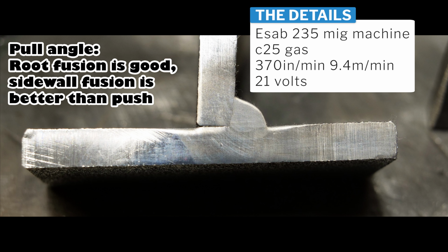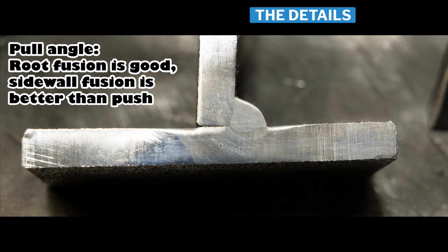So pulling, we can see that the weld isn't quite as flat. It's a little bit more roped up, but the penetration is actually better. There's no question that the root is fused, and it's fused beyond the root, so we actually do have penetration. And this is why in the previous break test that it actually broke at a higher level, is simply because more of the root was fused.